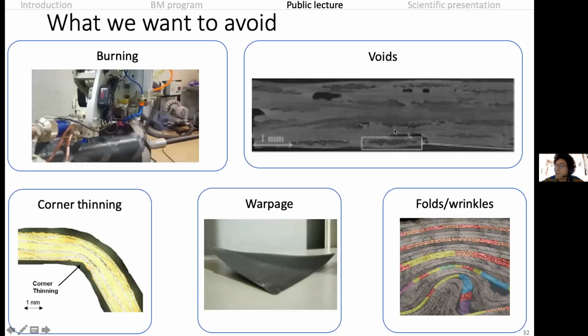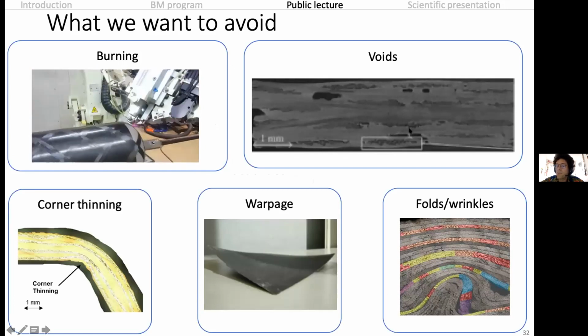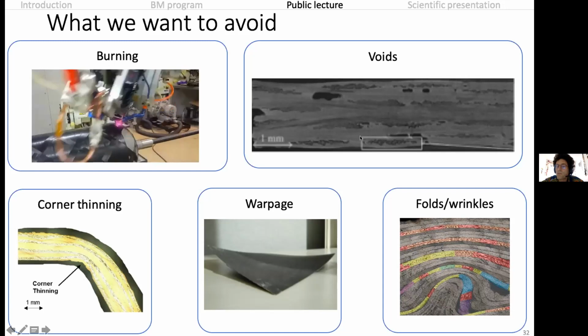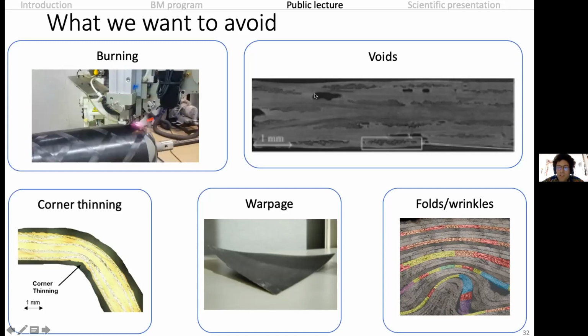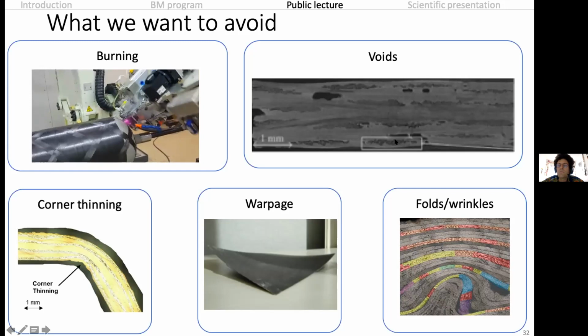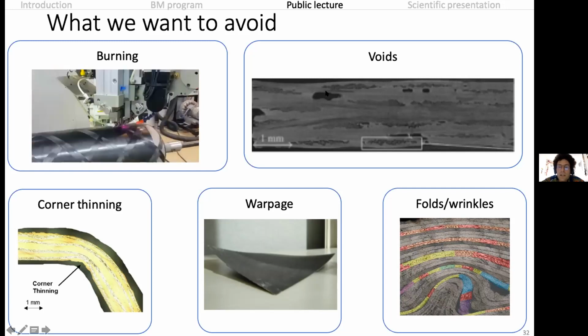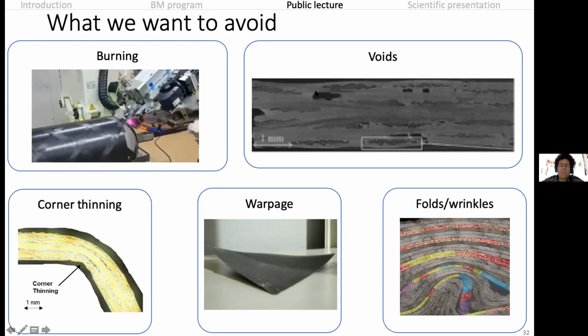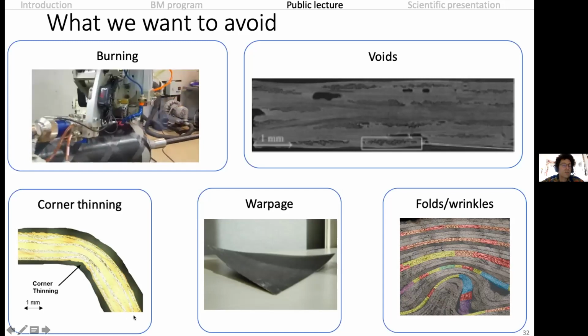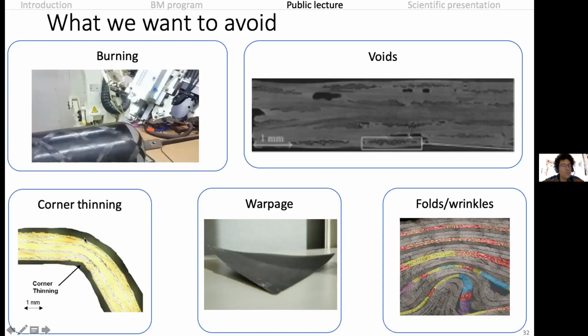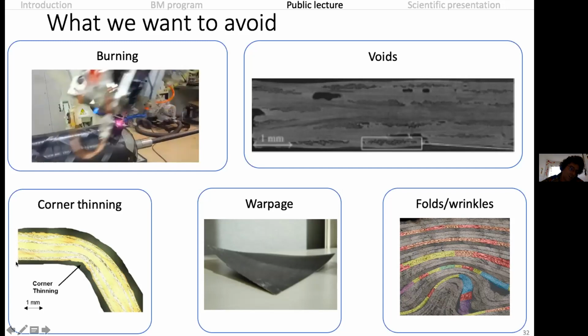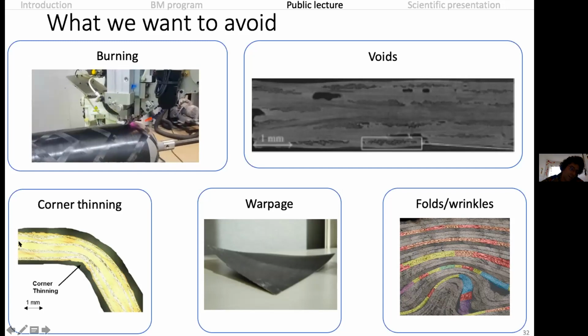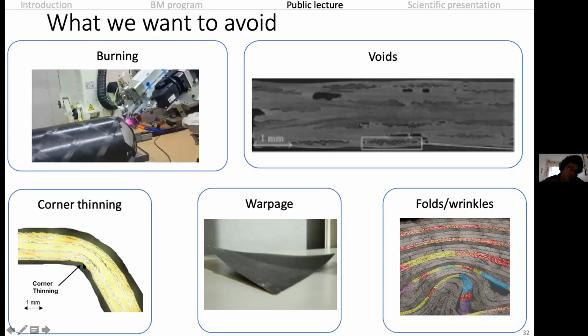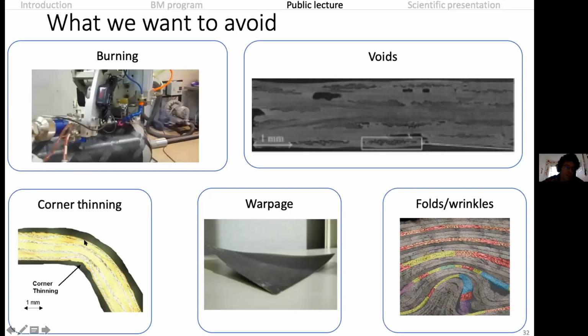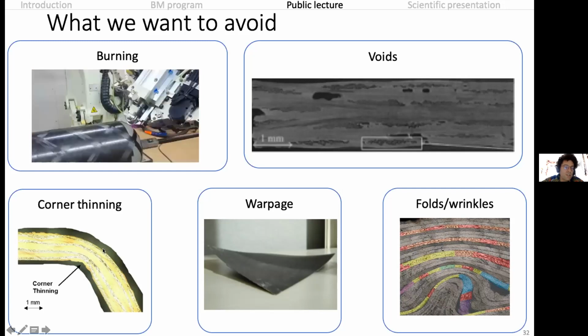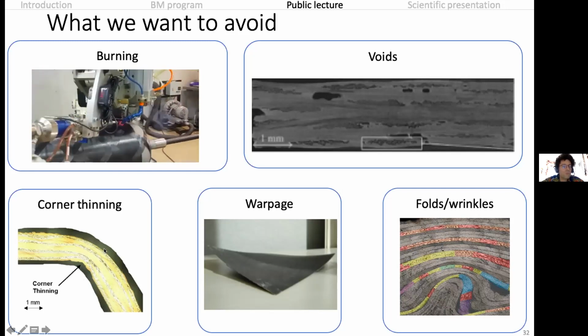You may have some voids, so you tried to put your resin inside your material, but it didn't go everywhere. There are some dry spots here. There's a big bubble here. This is a micrograph of a structure here, and you see that you have defects, you have bubbles, and this will be a weakness in the final structure. You may try to do L shapes, and you see that the flanges here have a given thickness, and the thickness in the corner is really thinner. So there's also a weakness here in the corner. So it's more of a geometrical defect here.